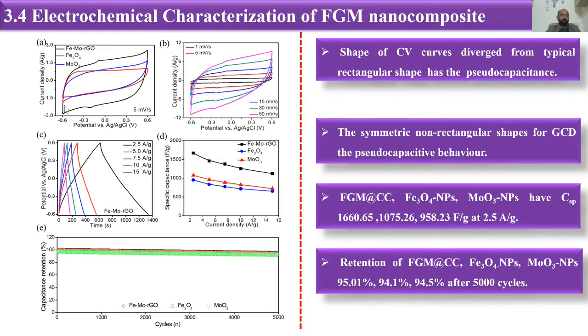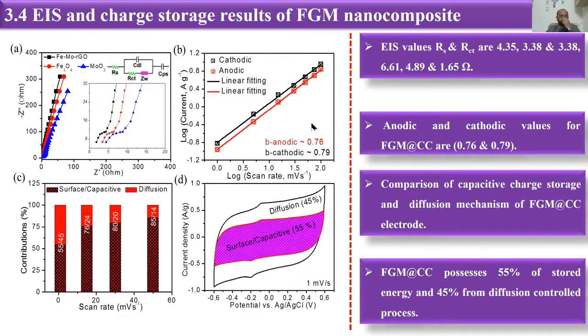And again, we have done EIS for FGM and our anodic and cathodic peaks for our system, and then we have done the charge capacitance and diffusion capacitance contributions to see how much charge is accumulated. So we have seen that the capacitive charge is about 55% as compared to the diffusion control process.